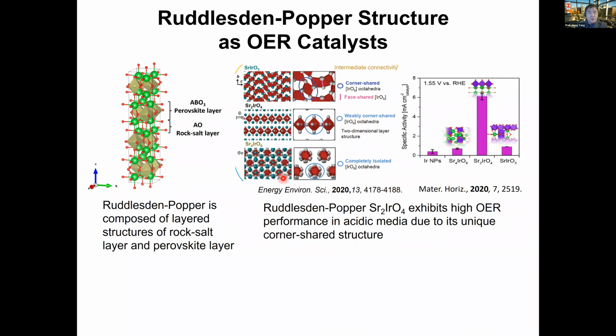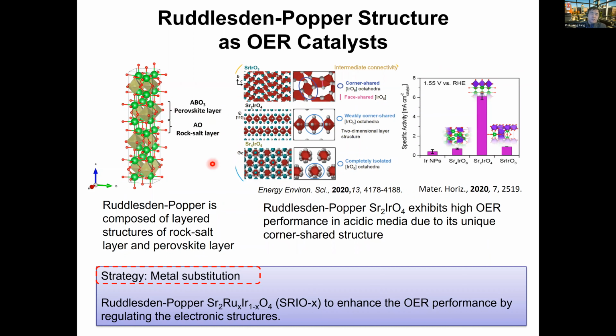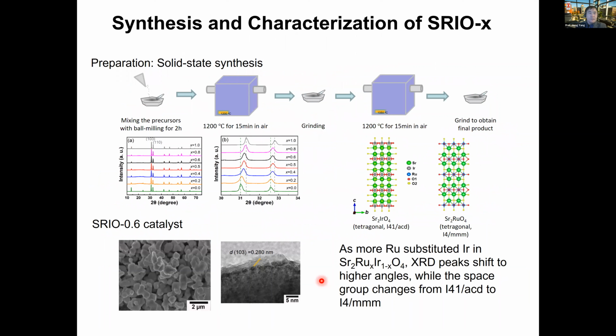So we tried to see, if you create a mixed site again, i.e. substitute the B site with partial substitution, what can we do, i.e. continue to improve the valence change in that particular site and see what happens. Okay, so the same synthesis approach is used in this particular case. We also see the peak shifted with the composition change. And interestingly, even though these two have similar tetragonal symmetry, they have a slightly different phase depending on whether it's ruthenium or iridium in this structure. Okay, so this is the one that we alluded to, and we think about whether they make a difference.